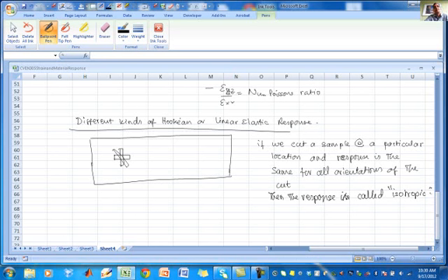So if you say, is steel isotropic? The question does not make any sense. We can say, am I going to use an isotropic model for steel? I'm going to treat the response of steel as being isotropic response. Then that's fine. So most of the things that we talk about are for models only and not for reality.